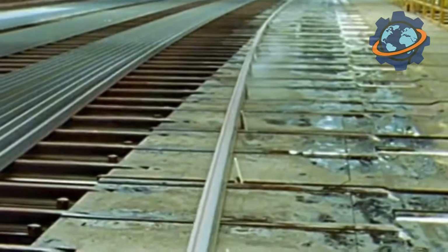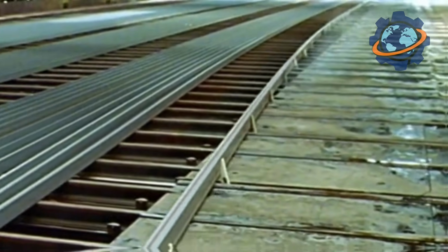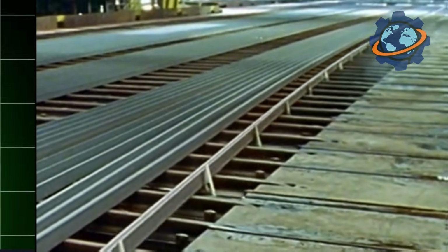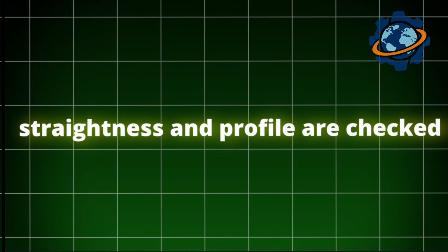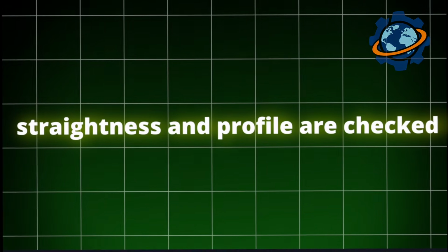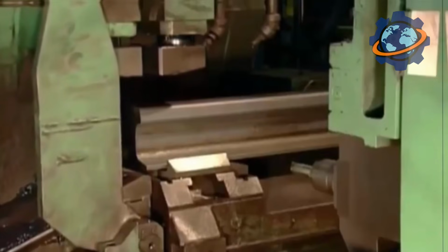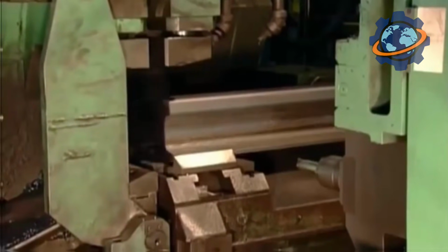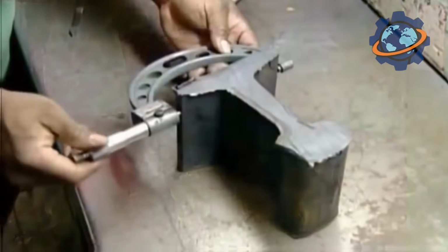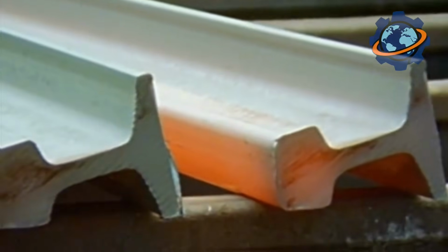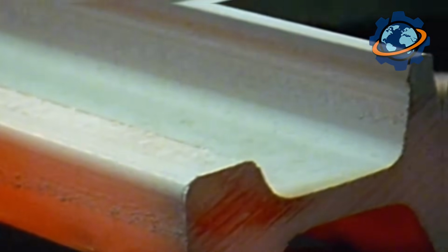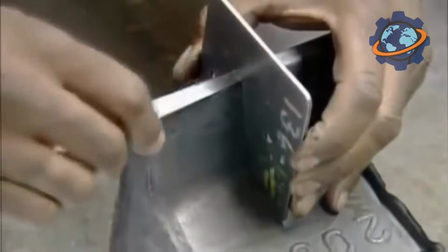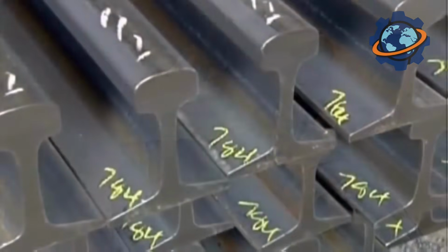Then, hardness measurements along its entire length to make sure the heat treatment was uniform. At the same time, its straightness and profile are checked. Laser sensors scan every inch, detecting even tiny warps that could cause vibration or wear. And finally, bend and impact tests. A piece of the rail is loaded with pressure dozens of times greater than the weight of a train to make sure it can handle any challenge on the route.